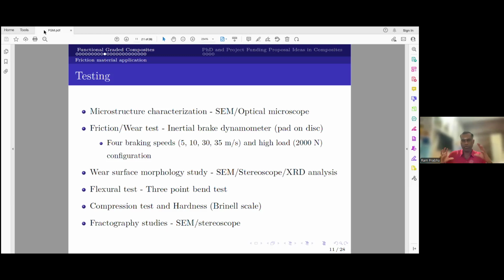And as you know, it's an axial brake. So there is a bending load, there is a compression load. So that's why the 3-point bend test and compression test are done. And we wanted to know whether the functional gradation has introduced the hardness variation. In other words, whether the strength and toughness properties are optimized. So we did the hardness test, and the flexural test and compression test. We looked at the fractography to prove that toughening happened inside the material due to the functional gradations. So this was the logic. Based on the logic, these tests are selected.